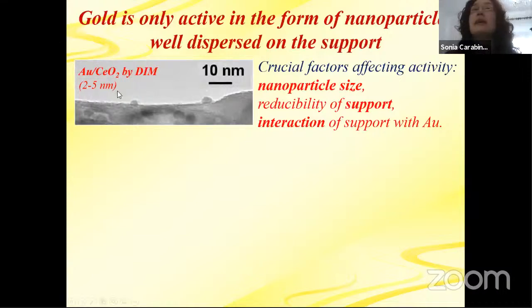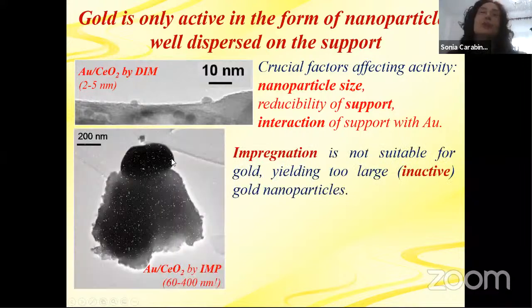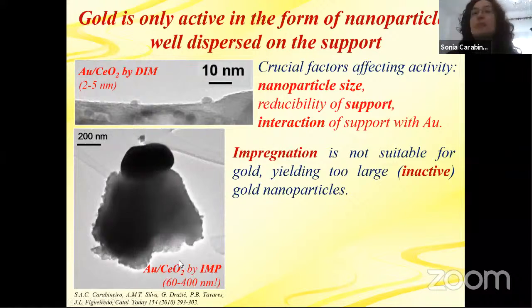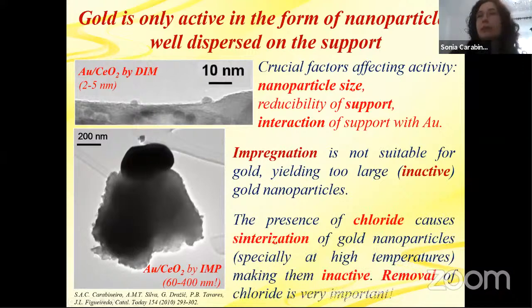So here we have an example of very small gold nanoparticles, 2 to 5 nanometers, on cerium oxide, prepared by a double impregnation method. I will explain later what it is. And we have here a large gold nanoparticle of around 400 nanometers, which is a lot, prepared by incipient wetness impregnation, which is a method that is not suitable for gold because it gives too large gold nanoparticles that are inactive. So that is the problem. And the presence of chlorides, because usually the gold precursor comes in chloride salts. The presence of chloride causes sintering of gold nanoparticles, especially at high temperatures, and makes them inactive. So the removal of chloride is very, very important.